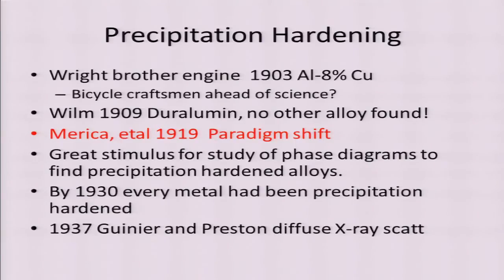And we don't know what they specified in terms of heat treating because it doesn't age harden at room temperature. So they must have either specified a slow cool or they must have heated it to about 200 centigrade. And in 1904, there was an aluminum bicycle in the St. Louis World's Fair. We've been trying to get a hold of it. We don't know where it is, but the Wright engine has been tested, and indeed it has precipitation hardened. It has the Guinier-Preston zone of something that has been heat treated, and not aged at just room temperature. So the craftsmen, in this case the bicycle people, knew about a way of getting hard aluminum, the rest of the world didn't.